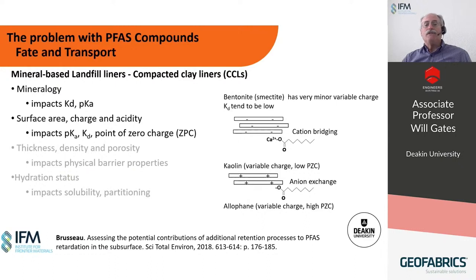The mineralogy and surface properties, such as surface area, surface charge, and surface acidity, impact how the PFAS itself will interact. For clay minerals with a permanent net negative layer charge, such as bentonites or the montmorillonites within bentonites, the adsorption of PFAS is largely limited to ionic bridging because they basically exist at concentrations below the CMC, but at pHs above the pKa.